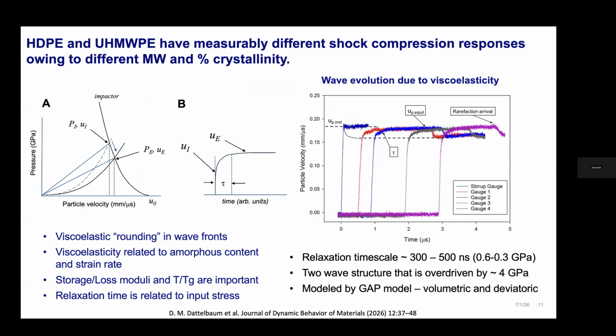So what does this look like in the wave profiles? On the right-hand side, I show some of our embedded gauge measurements. We basically measure the shock wave profile at the impact interface and then at a variety of depths into the material. And I believe this one is for high density polyethylene. Sorry, the zoom window is covering part of my PowerPoint slide. But what I wanted to show you here is that over time and distance, that initial wave in the material, which looks like a very clean, sharp, flat top shock wave, evolves into this rounded structure.